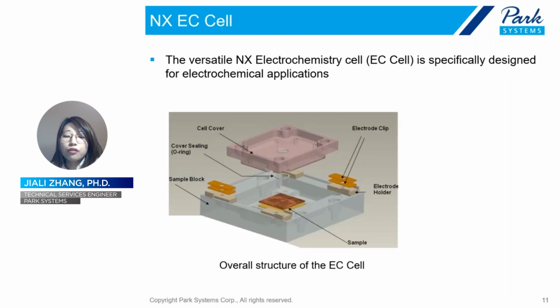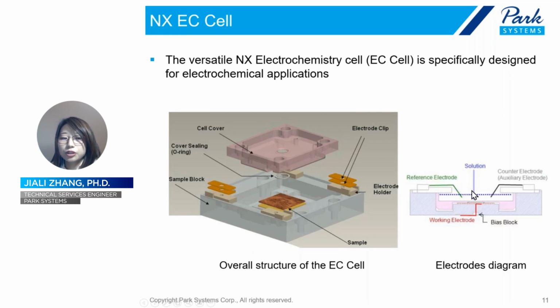So here shows you the overall structure and the individual components of the Park NX EC cell. The sample, or the working electrode, is mounted with a top cover and sealed with a thin silicone O-ring that securely prevents leaks to the back side of the sample. On the right side, these are electrode diagrams. You can use platinum iridium wire as a counter electrode and silver chloride as a reference electrode. They are all supplied in Park's EC-AFM starter kit, but any customized electrode can be connected to an electrode lead.